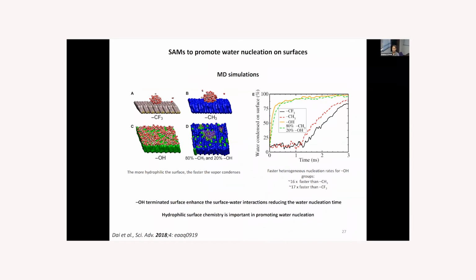It was shown already in the literature that SAMs promote water nucleation on surfaces. And it was shown with MD simulations, like here, where they have different methyl group terminated surfaces and OH terminated surfaces, and they could see the difference in the vapor condensation on the surface. For the hydrophilic OH terminated surface, you could see very nice and smooth adsorptive condensation of water molecules on top of the SAM. And for the methyl groups, only a very small amount of molecules would condense, in more like patches.